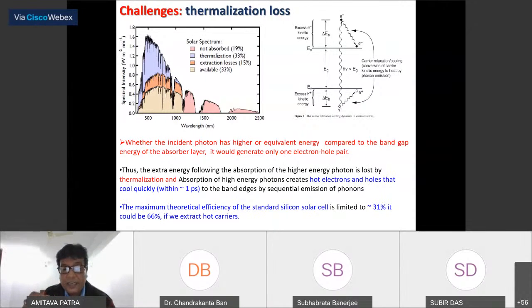And it takes place within 1 picosecond. What is 1 picosecond? That is 10 to the power minus 12 second. So that is called hot electron generation, hot carrier generation. So far, the theoretical efficiency of a solar cell is 31%. But if you can extract that hot electron before recombination, you can go up to 66% thermal efficiency. So people are now trying to develop a system where you can extract that hot carrier or hot electron before the recombination process so that the efficiency can be enhanced.